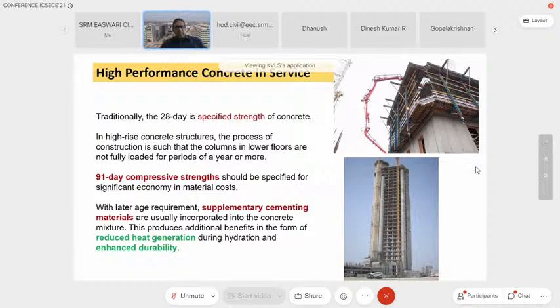So again, now people are starting to relook things where traditionally we have looked at 28 days of strength. Now, suppose I have a high-rise building that I'm constructing, where is the need for me to specify a 28-day strength? Because if I look at the columns at the ground floor, by the time they see loading, which is substantial, the age of concrete would definitely be more than 28 days. So why is there a requirement for concrete to achieve all its strength very early? So we are looking at now prescribing strength requirements more on a 91-day or a 56-day requirement, which basically relaxes this rush to gain strength and which allows us to use more supplementary cementitious materials, basically materials like fly ash and slag, in the concrete. It reduces the heat generated in these structures. And basically, I'm able to produce more durable structures with the use of these supplementary cementitious materials.